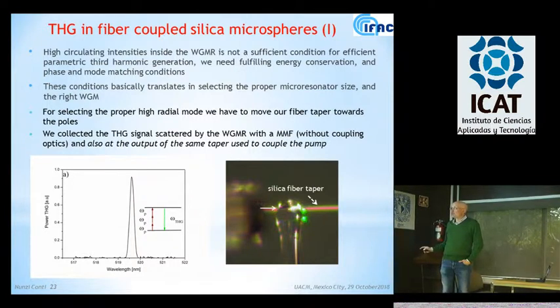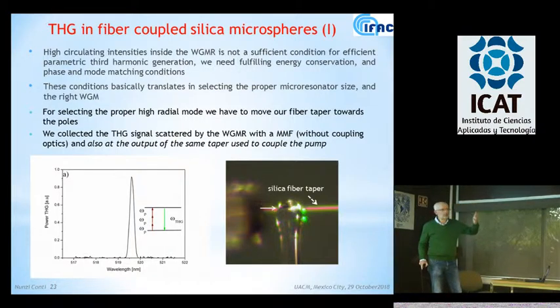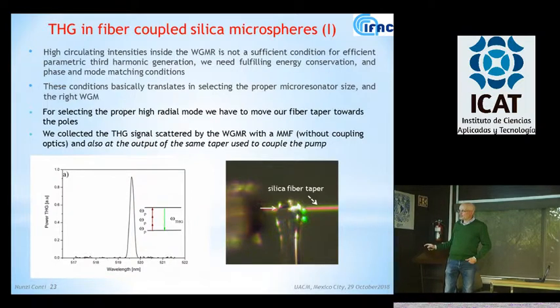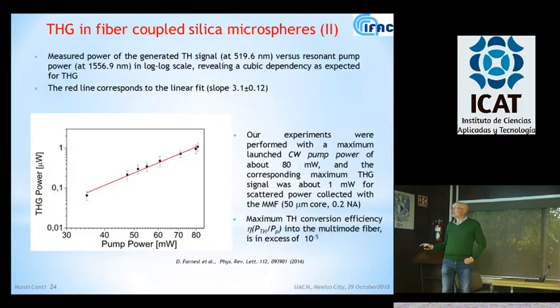we selected the right mode, but to excite that mode, we need this type of coupling device, so a fiber taper, because we could select a high order polar mode simply by moving the taper from the equator to a higher order mode. You see here two green spots. This is the third harmonic that is excited by exciting this higher order polar mode. I have not shown you how they look, but basically they have two peaks symmetrically placed versus the equator. And so it's the demonstration that we could really excite those modes, and we could have quite an efficient process.